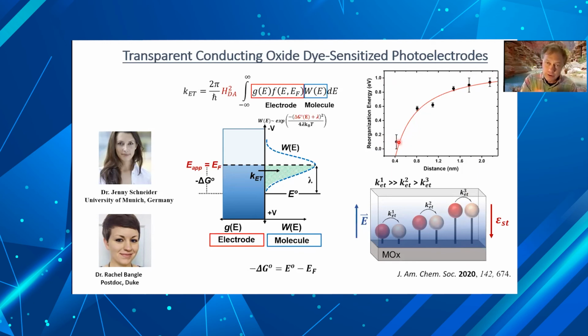But why we're excited about that is it says that if we can do catalysis or photoinduced electron redox reactions very close to the interface, the barriers that we normally encounter from the solvent stabilizing all this charge will be absent. And we have an opportunity then to drive reactions more efficiently. And I have to say it's a big departure for us, because when we started in our EFRC research, we always wanted to do catalysis as far from the interface as possible to try to prevent those back reactions. And now we're seeing that there's a real kinetic advantage to running the reactions closer to the surface.